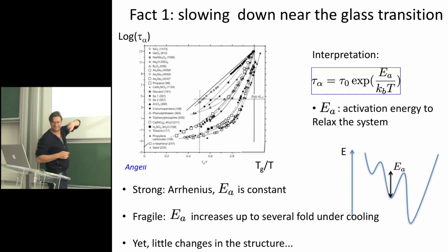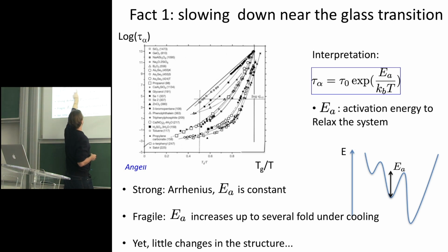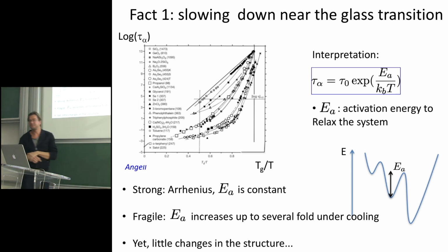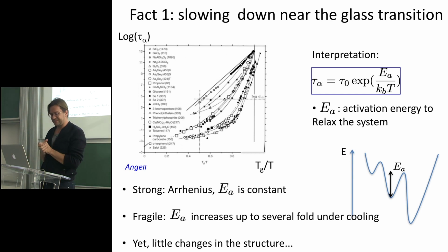So, okay, I'm not that tall, sorry. But if you have a strong liquid, on this plot, which is a log of time versus Tg over T, if it's strong, you just have a straight line. So silicate is, for example, the straight line over there. But those fragile liquids, you know, they seem to slow down much faster. So why is it that they do that? What's causing this increase of activation energy? And that takes place while there is no obvious change in the structure.